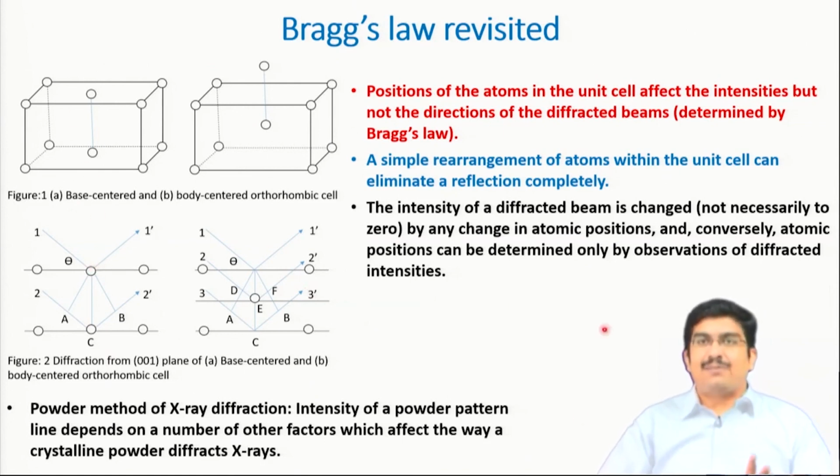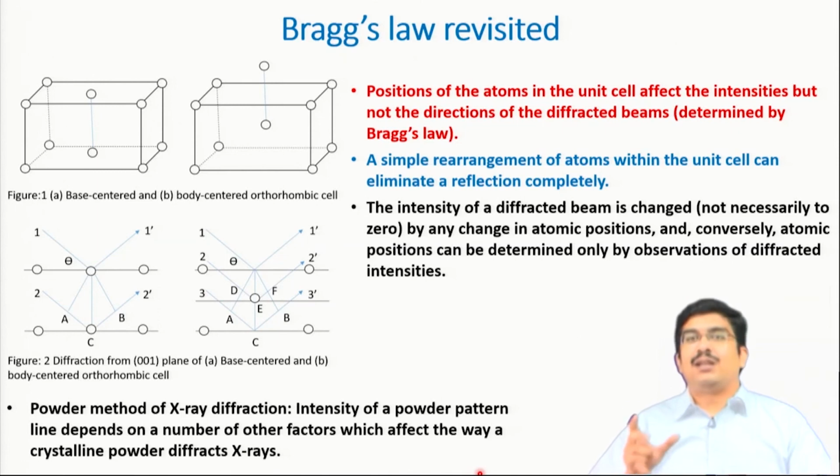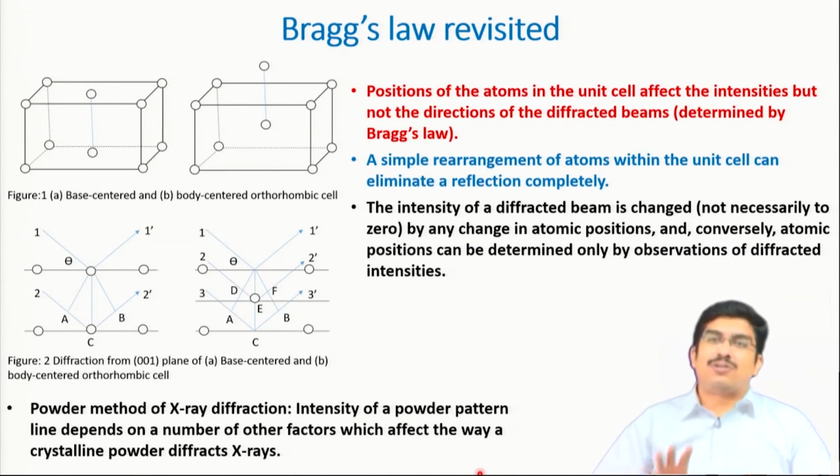So, this again tells you the same story, that Bragg's law is not enough to have a diffracted beam. Atomic arrangement also plays a role in getting a diffracted intensity.